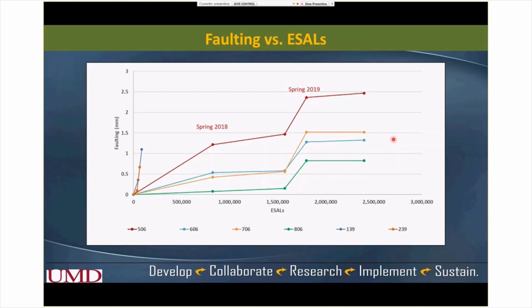So now in one of our tasks, we are using all the faulting results to develop faulting prediction models. We are also doing the same for fatigue cracking, but because for 506 through 806 we did not see any good cracks, we are still struggling with that because of the unavailability of crack data for those cells where we varied the fiber. But we have analyzed the faulting data and tried to create some models.